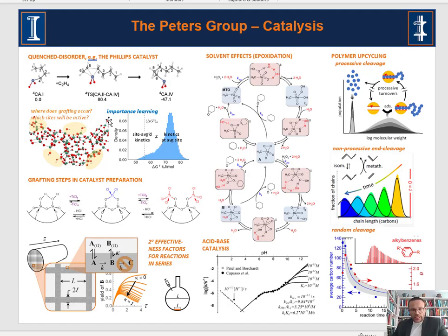Okay, the other area that we work in is thinking about catalysts in amorphous supports and just in general amorphous catalysts. So these are sort of orthogonal, mutually exclusive with most of the theoretical research that's being done in the catalysis field, but they are extremely important. So most people in catalysis are working on zeolites or metals or metal oxides, things that have crystalline surfaces. But these amorphous materials, every site is different, and when you do active site counting experiments, you often find that only like 1% of the sites are active, and yet these things are really important industrially.